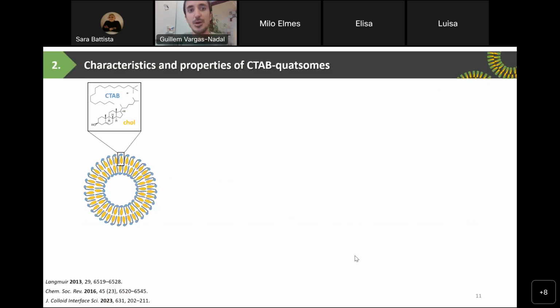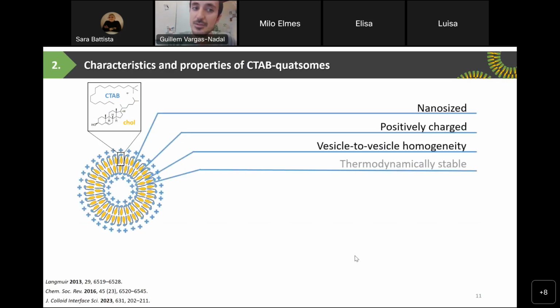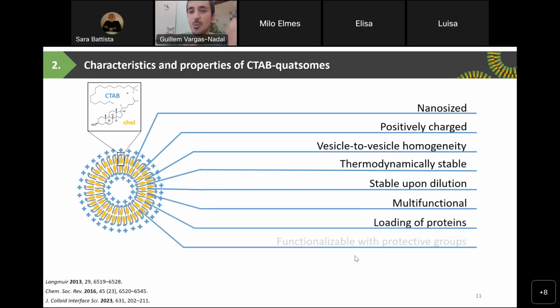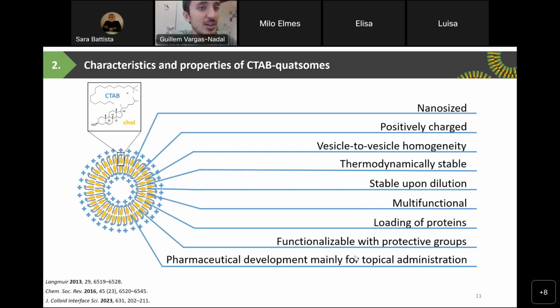First of all, I will explain some characteristics and properties of the CTAB quatsomes, which are composed of CTAB as a surfactant and cholesterol as a sterol derivative. In this case, these quatsomes are nano-sized, with sizes of about 100 nanometers. Also, they are positively charged. They have the CTAB, which has a permanent positive charge. They are homogeneous from vesicle to vesicle. And also, they are thermodynamically stable. They are also stable upon dilution. They can be multifunctional. Also, they can load different proteins, and they can be functionalized with protective groups. And these quatsomes are currently being developed for topical administration as pharmaceutical drugs.